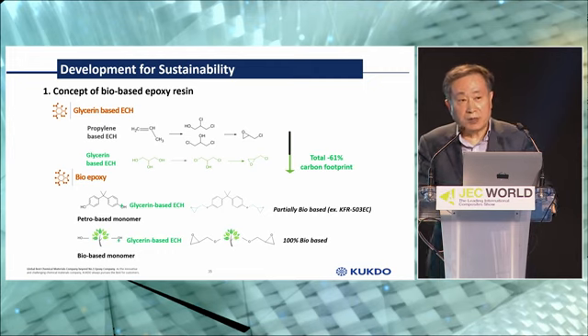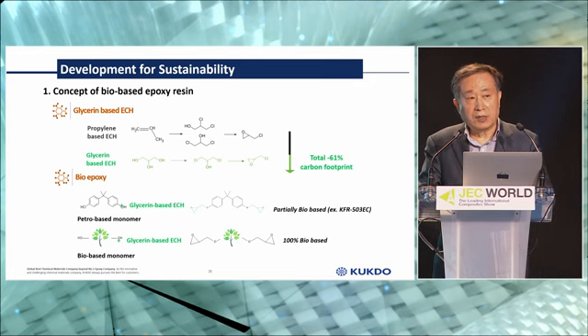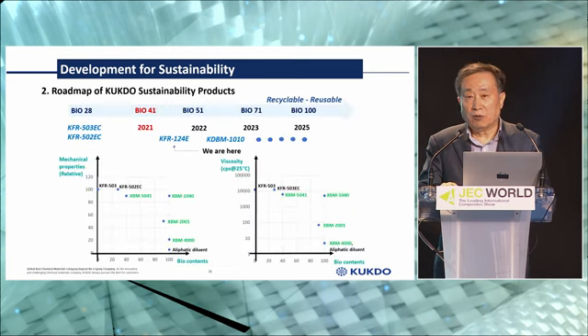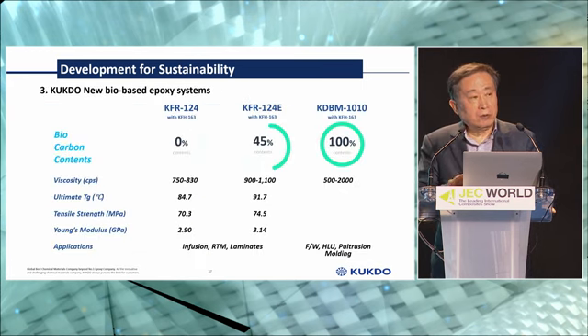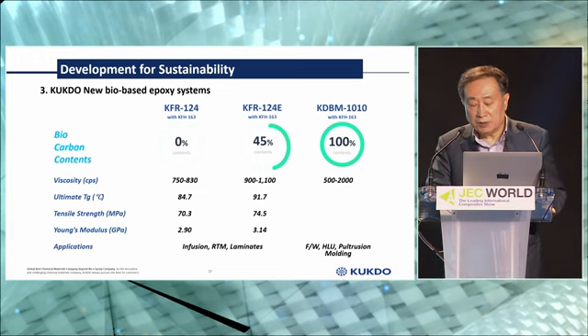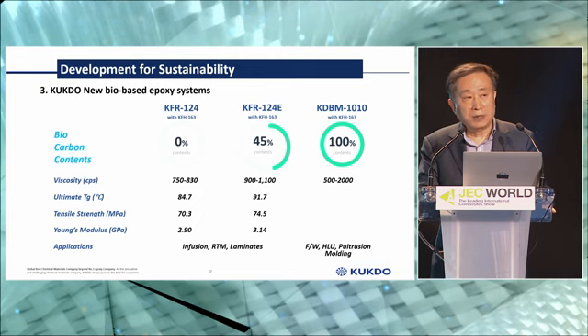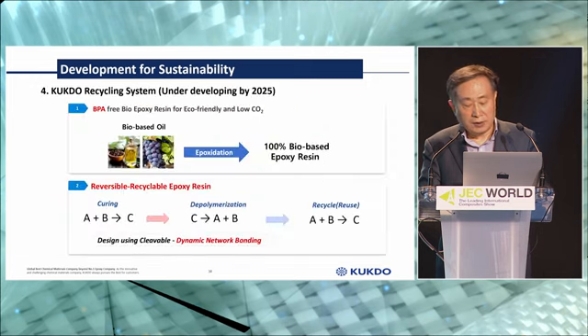And also for aerospace, we are trying to make it with the infusion system or prepreg system based on these bio epoxies. And our target for bio epoxies by 2025 is a 100% bio system, which means not petrochemical epoxies. Already for wind blades, some wind energy customers we are supplying and evaluating with our system, with bio content around 45%. You don't need to change cure conditions, and you can have high performance cured properties without difficulties.